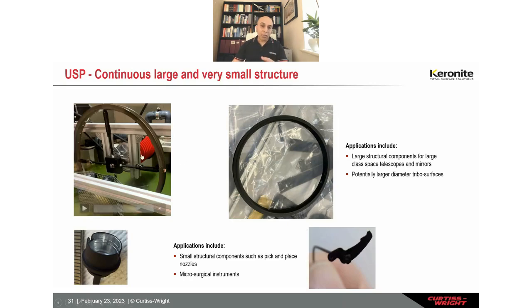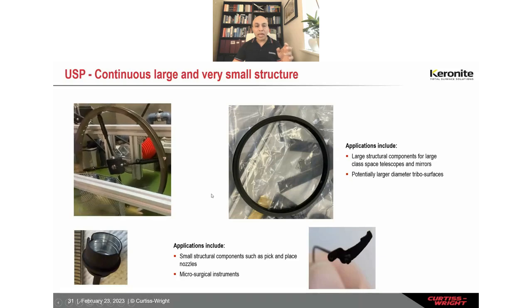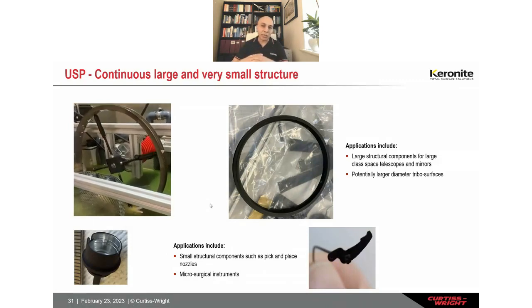This is a mock-up of a large disk. This is just a 24-inch diameter aluminum disk, for example. You can see those. So the beauty here is the whole part is not immersed in the electrolyte as you would do in normal PEO systems. Only a segment is being coated. You can see those plasma events at the bottom here happening here, there. So only a small segment is being coated and continuously rotated like the Millennium Wheel.